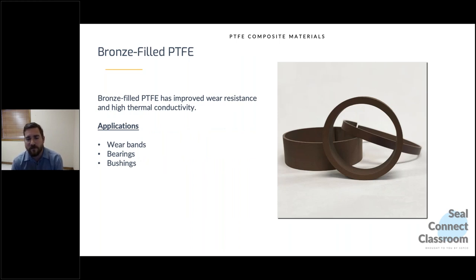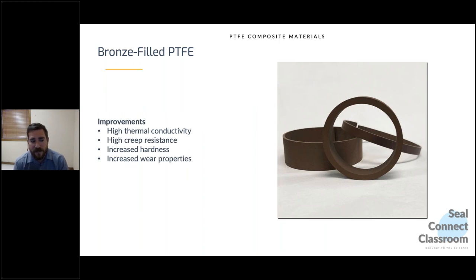So bronze filled PTFE, again, another pretty common industry standard material, improved wear resistance and really, really good thermal conductivity. As you imagine, 40% or 60% bronze filled PTFE, it's going to dissipate that heat very quickly, which is why we primarily see this material as a wear band material, where it's going to see a lot of frictional heat and a lot of wear. It's good for bearings, it's good for bushings. We see this in bearings for pillow blocks, or almost exclusively when PTFE is used, it's going to be a bronze filled PTFE. Yep, because it's that high thermal conductivity, high creep resistance, increased hardness. So you get overall increased wear performance as a result of that.